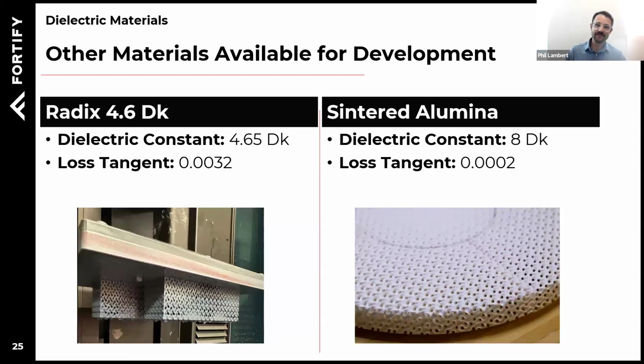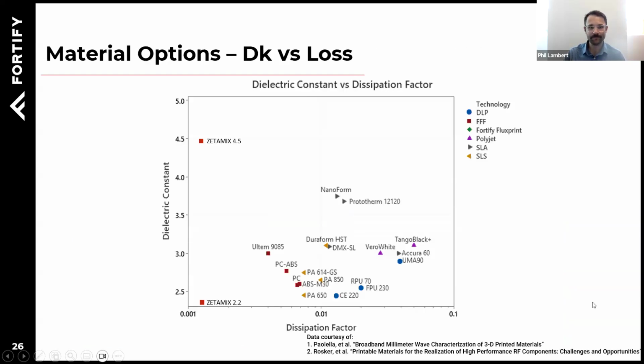And just to quickly touch on these materials once again, the material on the left is the Radix 4.6, dielectric constant of 4.65 and a loss tangent of 0.0032, in development, available for prototyping right now. And on the right, we have our sintered alumina material, which has a dielectric constant of 8 and a very low loss tangent of 0.0002. This material is also earlier in our production pipeline, but available for doing all different types of lensing applications. And I'll show you how we do it in a little bit.